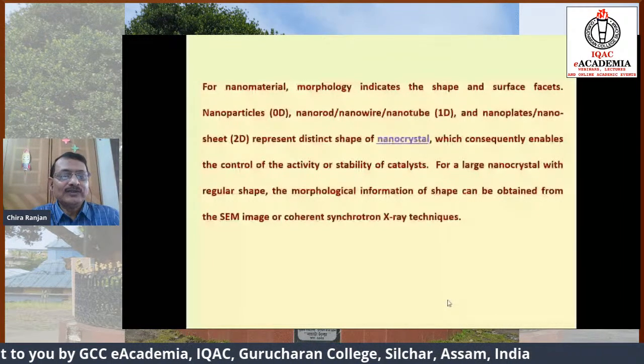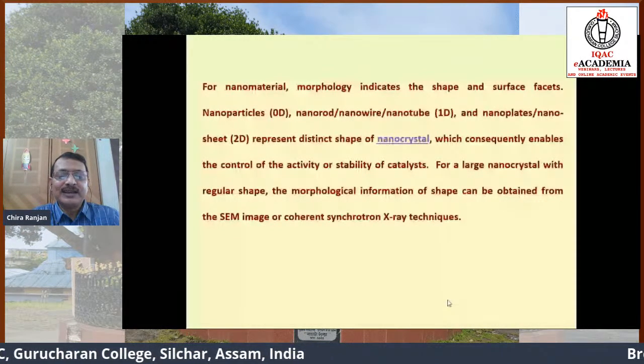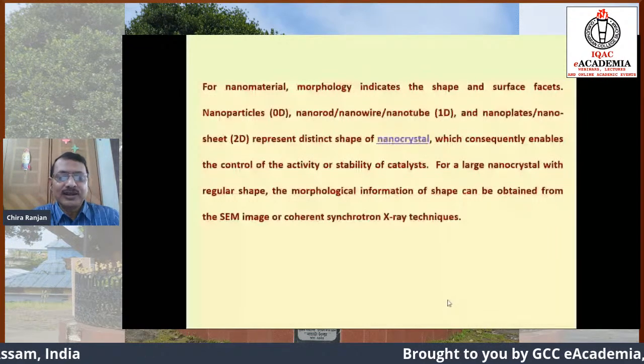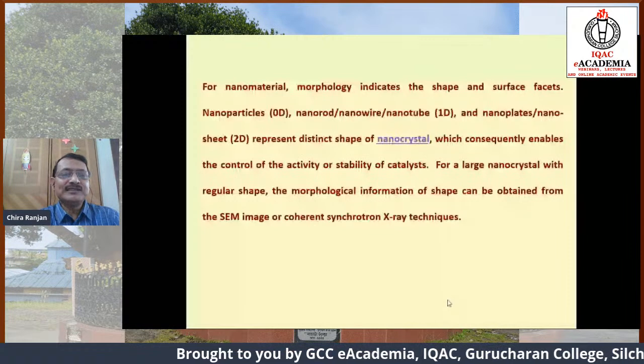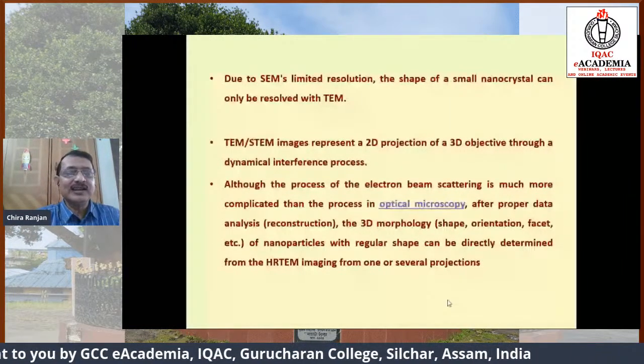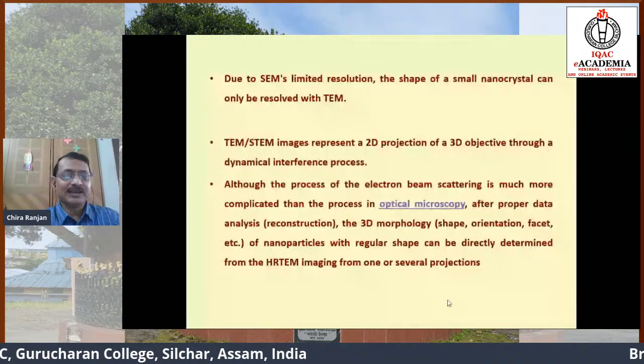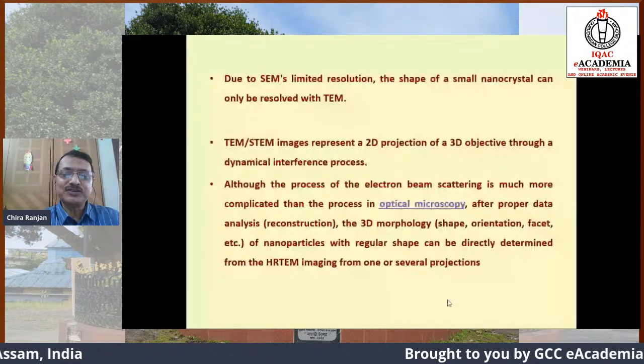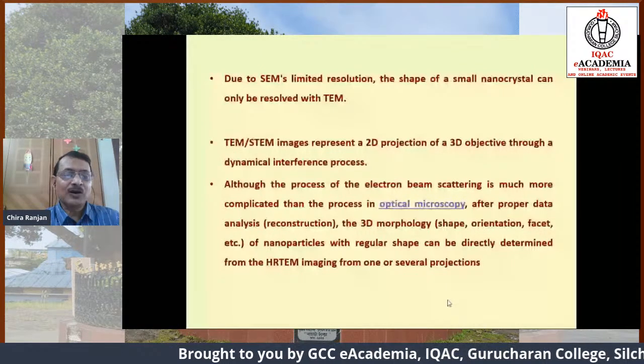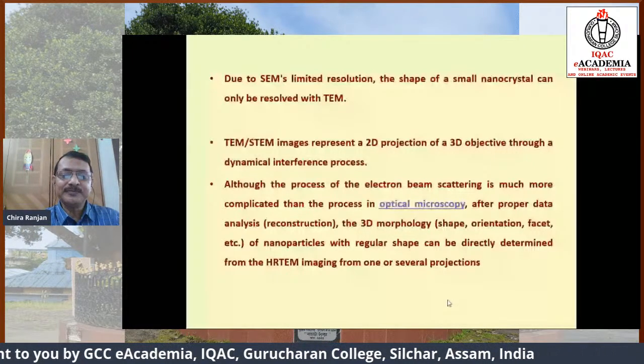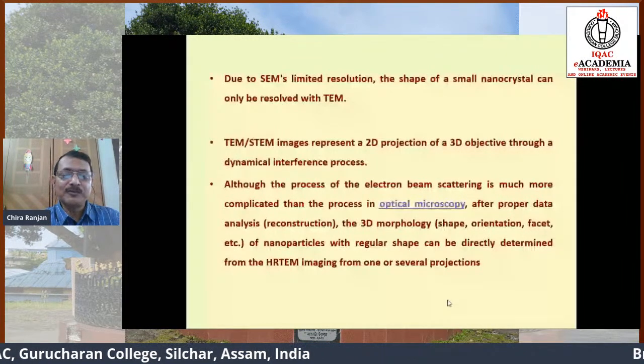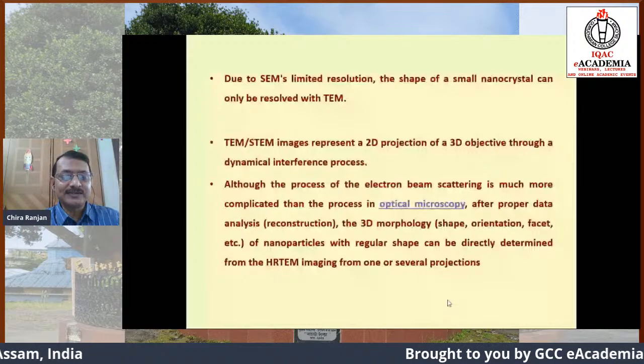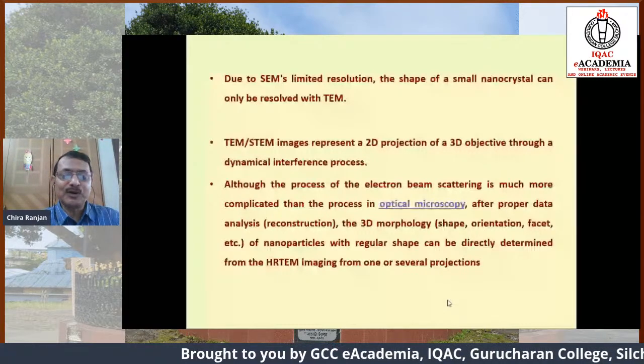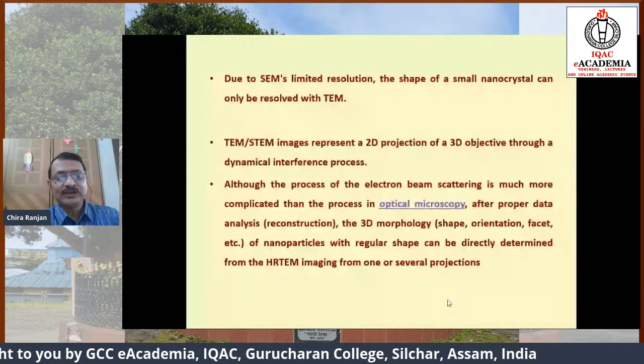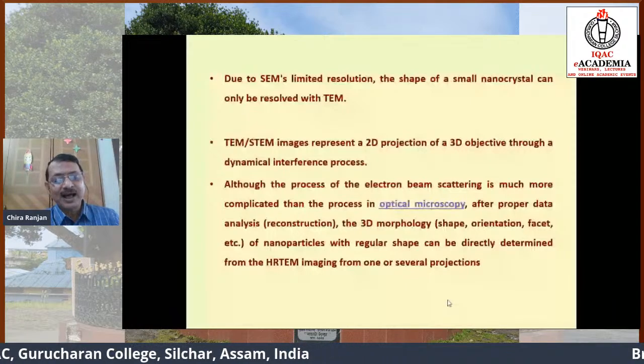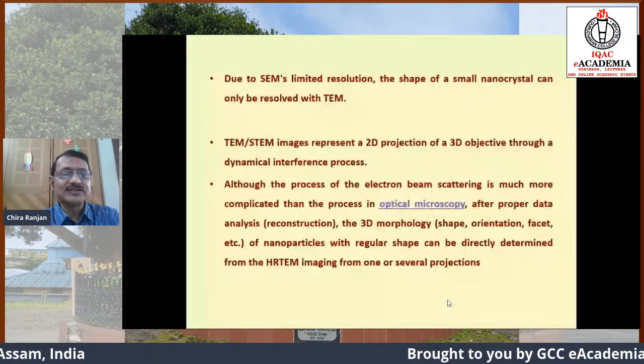For a large nanocrystal with regular shape, the morphological information of shape can be obtained from the SEM image or coherent synchrotron X-ray technique. Due to SEM's limited resolution, the shape of a small nanocrystal can only be resolved better with TEM. So TEM images represent a 2D projection of a 3D object through a dynamical interference process. Although the process of electron beam scattering is much more complicated than the process in optical microscopy, after proper data analysis, that is reconstruction, the 3D morphology, shape, orientation, facets, etc. of nanoparticles with regular shape can be directly determined from high-resolution TEM imaging from one or several projections.